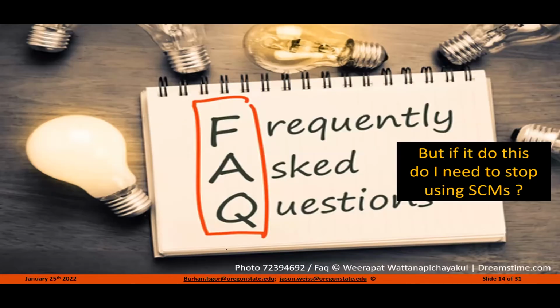But in addition to this, one of the frequently asked questions that we've gotten when we're talking with state highway agencies and other groups about this is, if I use a Portland limestone cement, does that mean I need to stop using SCMs? And the simple and most direct answer to this is no, right? Keep using your SCMs if you're using a Portland limestone cement. So you're going to get a 10 to 12% reduction in carbon by simply shifting from an ASTM C150 cement over to a C595 cement.